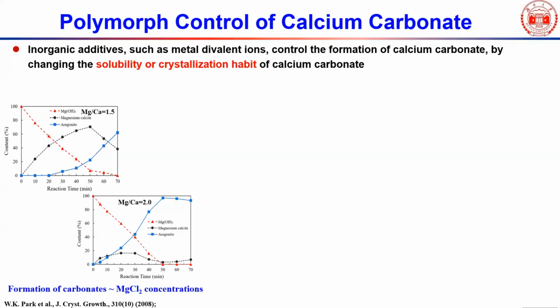Well, so how can we really control the formation of different calcium carbonate? First, thermodynamically, we established a model and then tried to add different additives or change the environment to get different polymorphs of calcium carbonate. We found that when we add some inorganic additives such as metal divalent ions, like magnesium and zinc, they can control the formation of calcium carbonate by changing the solubility or crystallization habits of calcium carbonate.